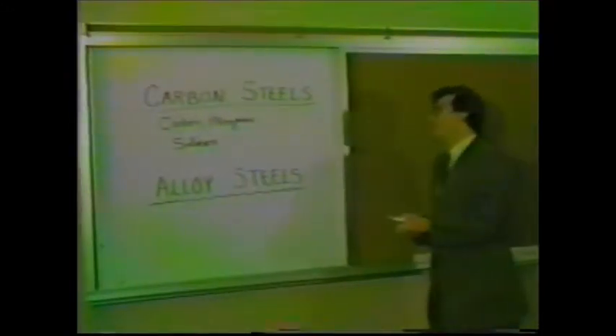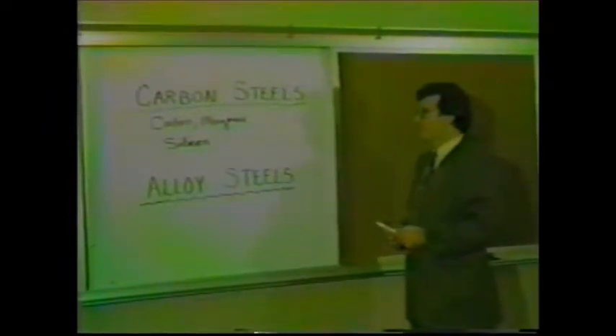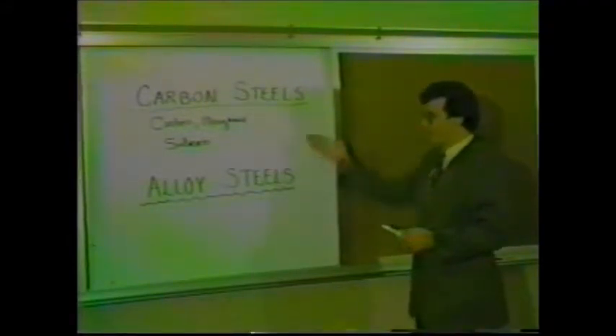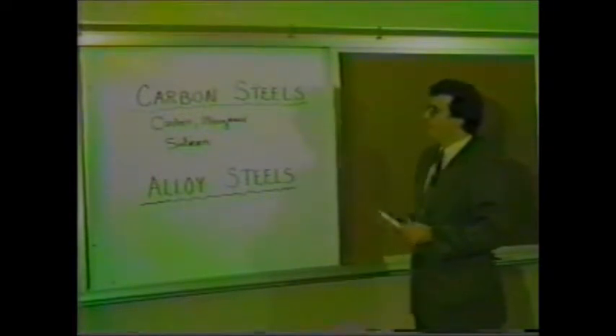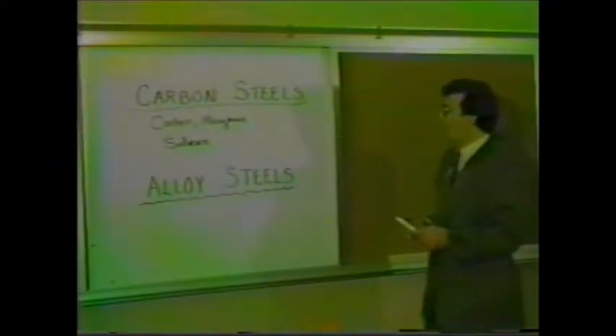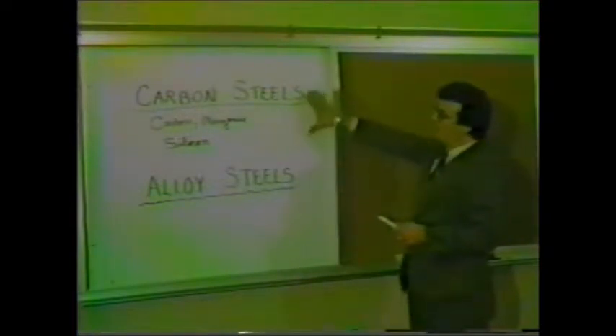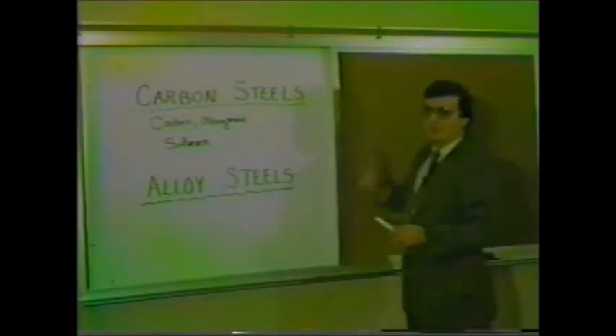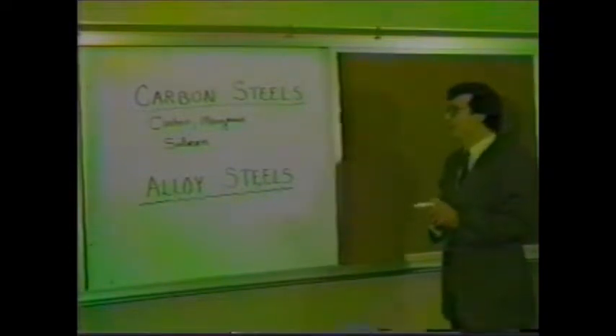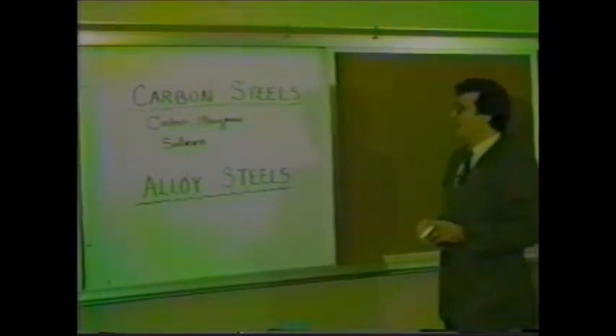One more important element in carbon steels involves the choice of silicon. Now, certain grades of steel are ordered specifically without silicon, and these steels are generally called coarse-grained steels in the carbon steel family. And the presence of silicon with other elements are called killed steels, and when you have aluminum or vanadium or columbium in there, these steels are also called fine-grained steels. Now, again, with carbon steels, you have a choice of using killed steel versus non-killed.